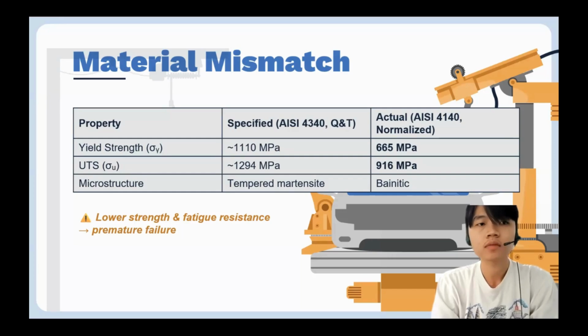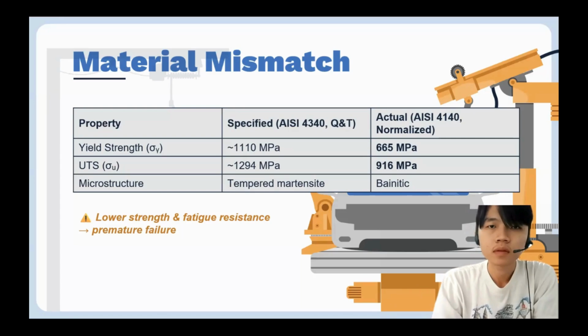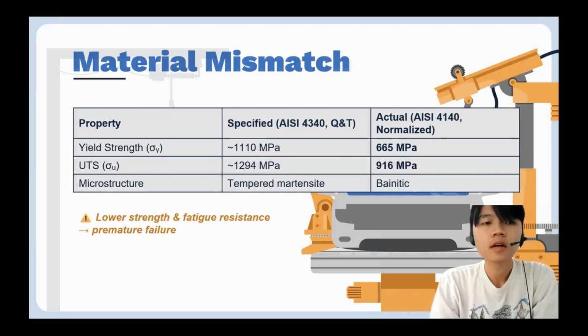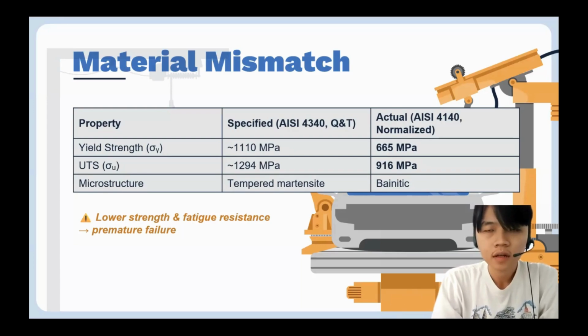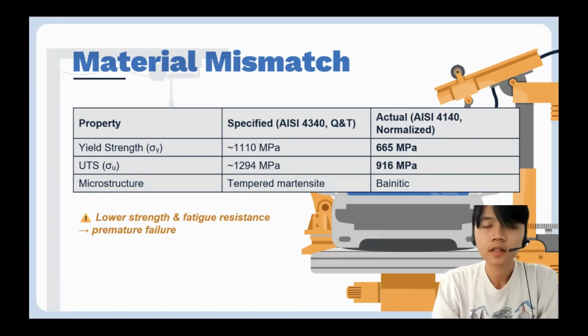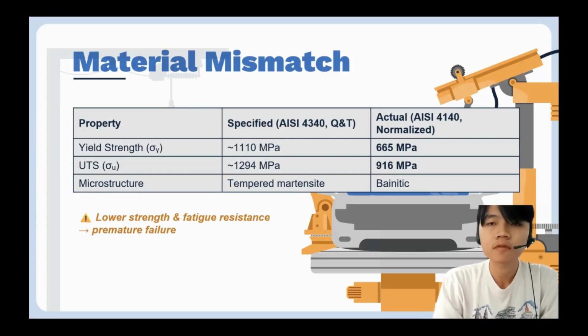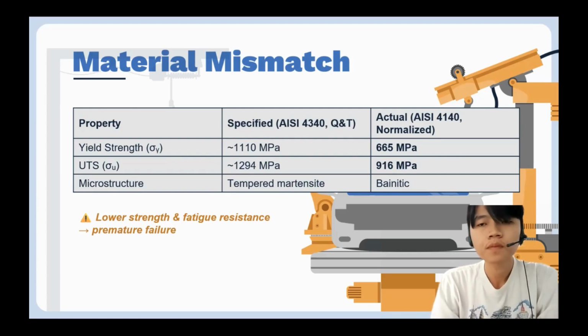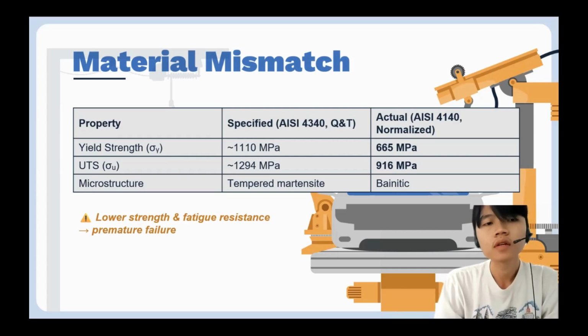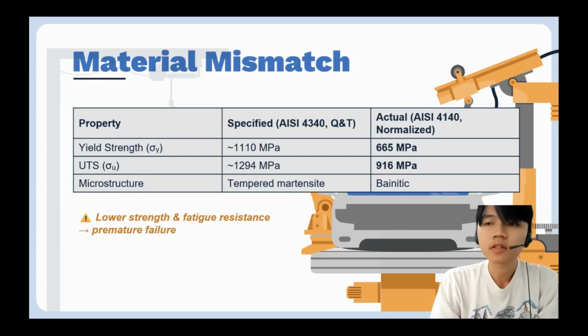When we compare the actual material to the specified one, the cause becomes much clearer. The design required AISI 4340 steel in a quench and tempered condition, and this has a high yield point and very excellent fatigue resistance. Instead, the shaft was manufactured from normalized AISI 4140 steel, and its yield strength is only about 665 megapascals. Compare this to the 1110 megapascals of the specified alloy.